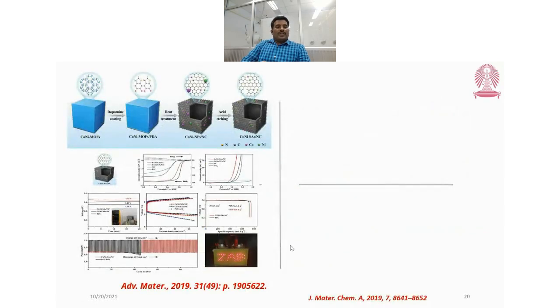This is a carbon nanotube MOF. First they synthesized the MOF with cobalt and nickel along with carbon nanotubes. Then the surface was coated with dopamine. During the pyrolysis, the reactive active species of cobalt and nickel anchored on the cubic surface. The excess reactive oxygen species were removed by acid etching. Then this MOF has excellent bifunctional activity as well as better performance towards a zinc battery.